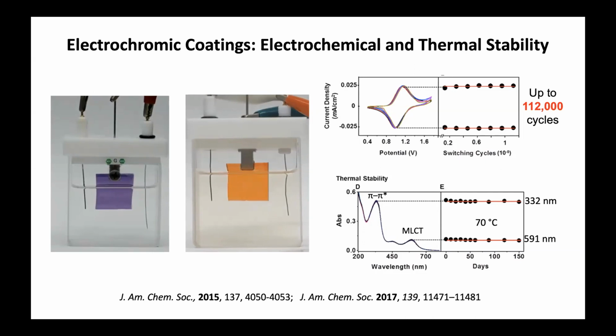The films, if you want to apply them one day, they have to have high stability. And here we see the stability experiments that we have performed. Here's just a simple CV of a film that contains iron. So you oxidize the iron, you reduce it, and a postdoc, Sanjit, has shown that you can do that more than 100,000 times. Thermal stability of the films is also quite impressive.